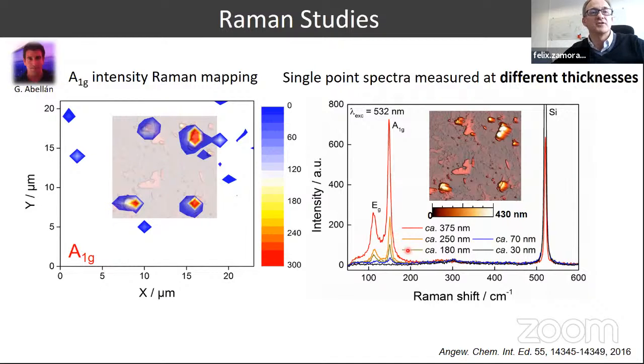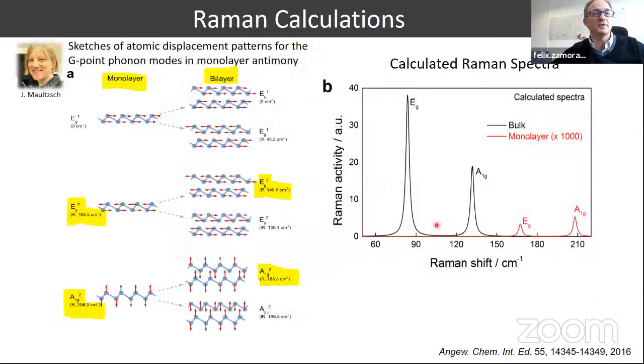In order to understand these results, in collaboration with Janina, she calculated different structures of antimony, monolayer, bilayer, and so on. Comparing the results, she ended up with this explanation in which, if you compare just the bulk situation and the monolayer one, we observe something that we observe also in the experiments: the intensity of the signal dramatically decreases by a factor of 3, sorry, 3 orders of magnitude.